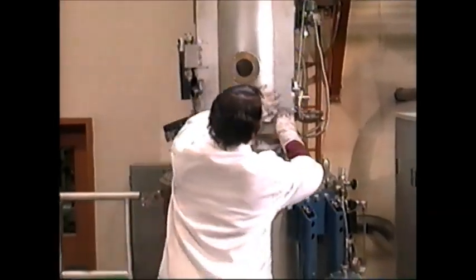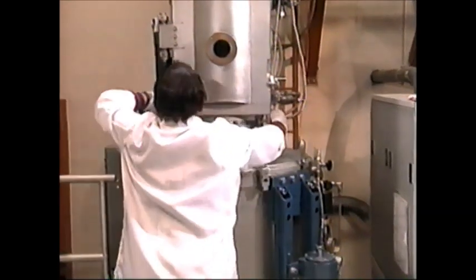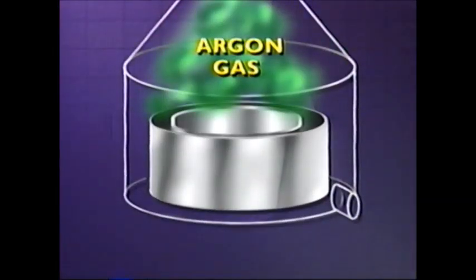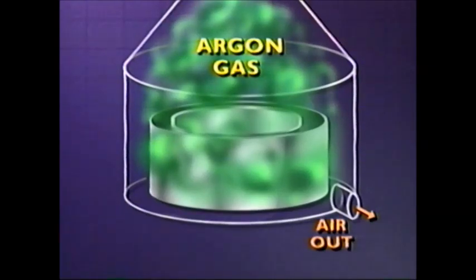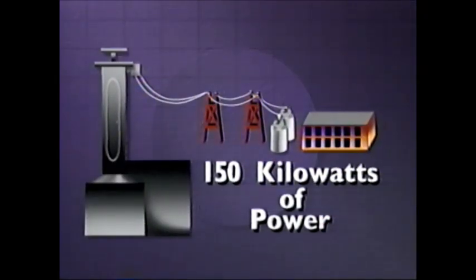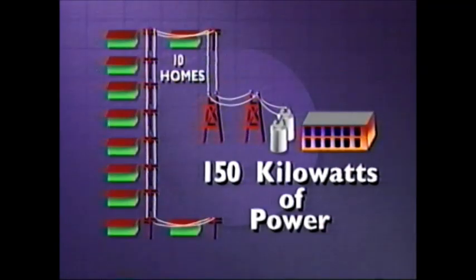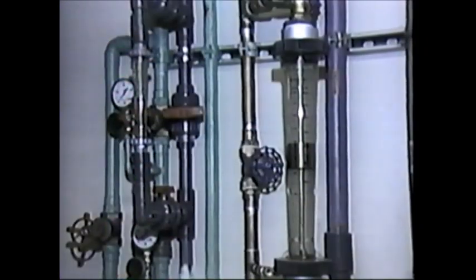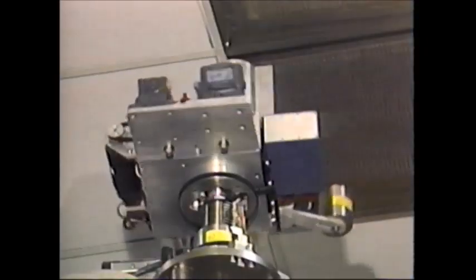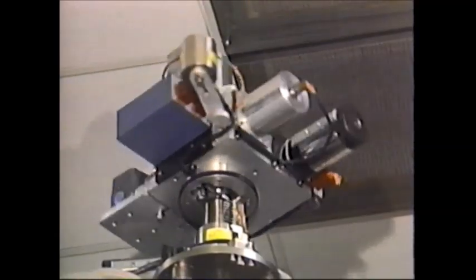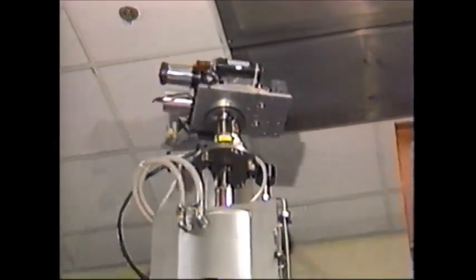Once the charge has been placed in the furnace tank, the furnace is closed. Then argon, an inert gas, is pumped into the furnace. This forces all of the air out and prevents the molten silicon from reacting with any contaminants. A typical crystal furnace requires about 150 kilowatts of power, enough to power 10 homes, and a continuous flow of recycled cooling water. Computer-controlled motors rotate the seed crystal that is suspended from the top of the furnace in a counterclockwise direction, while rotating the crucible clockwise. This rotation begins the drawing process.